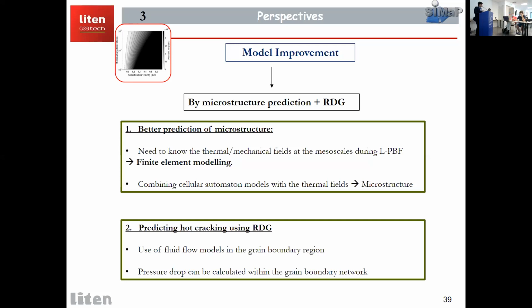We can also use these predicted microstructures and collaborate it with the RDG model to finally estimate the pressure drops which are in the intergranular regions of the material. For example, using different fluid flow models, we can have an estimation of what are the pressures needed to achieve a critical point after which you might have cracking. So pressure drops can be calculated within the grain boundary network using different fluid flow models.